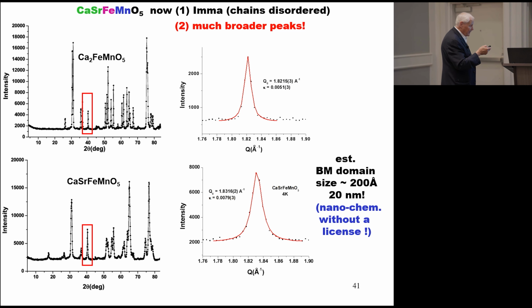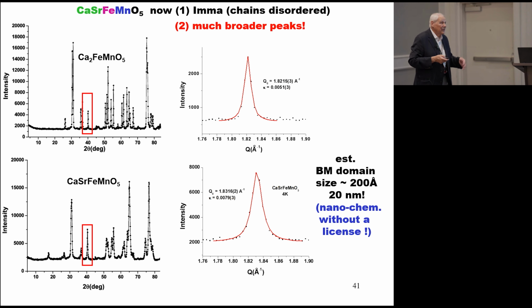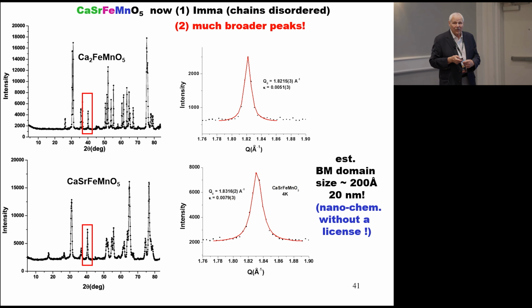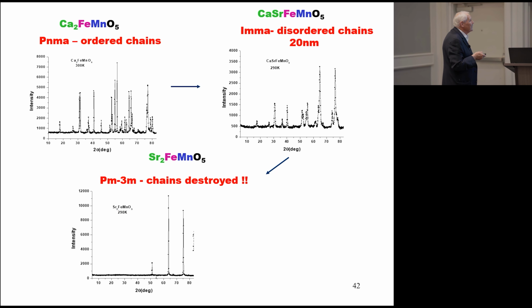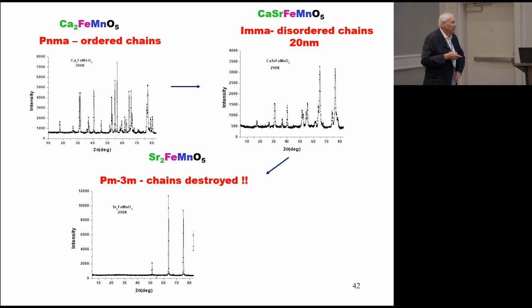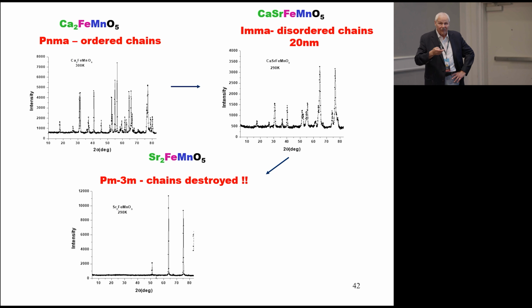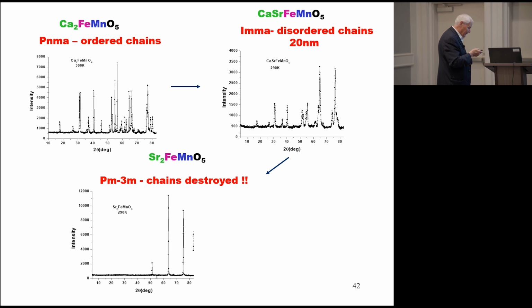And sure enough, by fitting that peak to a Lorentzian, it actually fits pretty well, we can estimate a domain size of about 20 nanometers. So we're doing nanochemistry without any effort at all, no fooling around, just changing the chemistry. Okay, and then finally, if we substitute all strontium on that site, we destroy all the chains, we completely destroy it. We're back to Pm-3m.